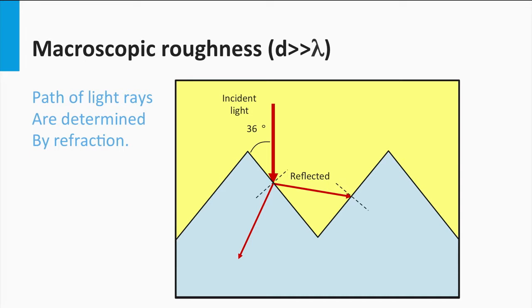For example, for light that is perpendicularly incident, light that is reflected at the textured surface can be reflected at angles in which the trajectory of the light ray is incident somewhere else on the interface. Here, part of the light will be transmitted into the layer and effectively less light will be reflected in reference to a flat interface.